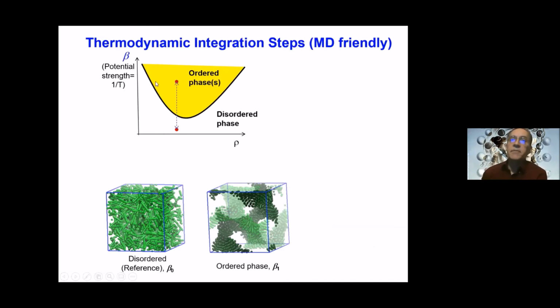So in some phase diagram, say these are two thermodynamic parameters, this maybe density, this is something like, say, beta, the reciprocal temperature, so that for low values of beta, you have a disordered state, and for high values of beta, meaning low temperature, you have the ordered state. One way you can get the free energy change between these two is by going along that line. But if you do it in either direction, you will encounter huge hysteresis because it's a first order transition, and you won't be able to get a reliable free energy difference. So this doesn't work. You basically need to go into another dimension.